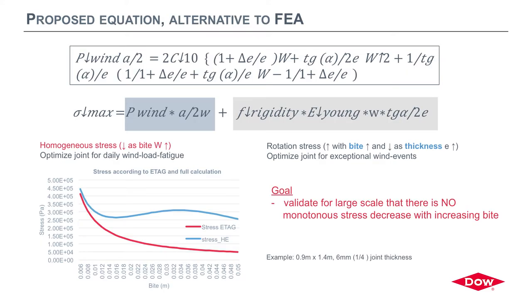We propose a new equation that takes this into account. At the top you can see the full equation incorporating the hyper-elastic character of the silicone. The second, bottom one is a more intuitive and comprehensible equation. We have the original term from the ETAG equation, plus a new term that includes all the aspects I described, including the influence of the joint aspect ratio captured by a factor we call the rigidity factor.